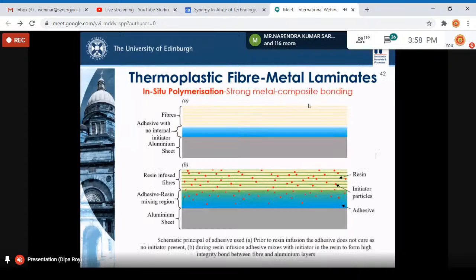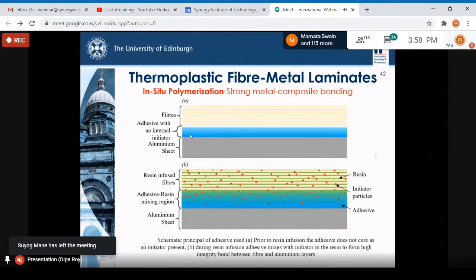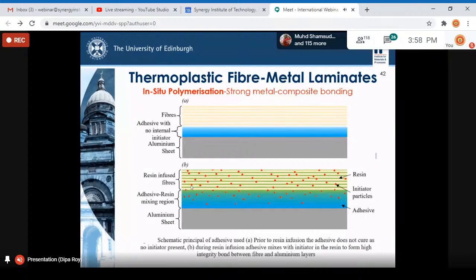Now, this was our methodology. We took the metal alloy and had a bonding layer, or an adhesive layer, but the adhesive did not have any curing agent. We didn't have any hardener in the adhesive. So when we infused the resin, the initiator present in the resin cured the adhesive. So there was a bonding between the adhesive layer and the resin matrix. So there was in situ bonding between the metal and the composite during manufacturing. This was a very interesting way of bonding the metal with the composite, and we were very successful in